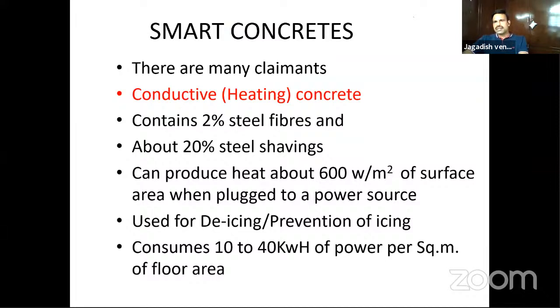Next, there are a lot of concretes that are used for specialized applications, smart concrete, particularly conductive concrete. This is basically a heating concrete. For this concrete, use 2% steel fibers and 20% steel shavings. Almost 22% of steel you use inside the concrete. What you do is plug that concrete into a power source. It will get heated up. What is that? The steel shavings inside the concrete. These are particularly useful for cold countries wherein you want to de-ice the concrete surface. So you heat the steel shavings, you heat the concrete such that all the icing will melt. You do it for de-icing purposes. And per square meter, it seems like 10 to 40 kilowatt hour of power it consumes.